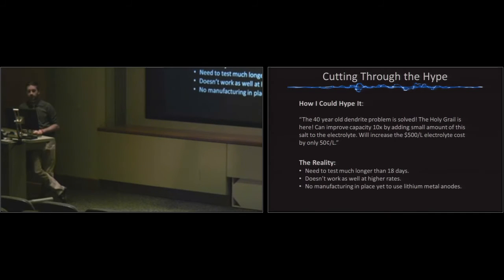In reality, you need to test these for a lot longer than 18 days. So 18 days is a pretty long period by the literature standards, but it has to go a lot longer than that to actually be usable in an actual battery. We tested it at higher charge rates, and it didn't work. It still worked pretty well, but not quite as well. And so we would need to iron out some of those problems.